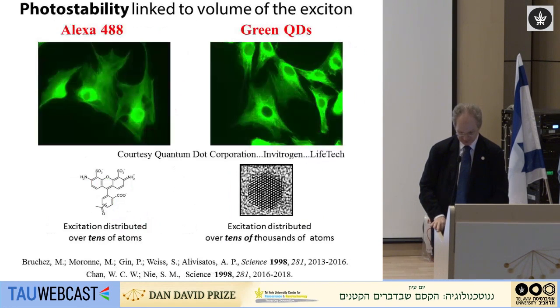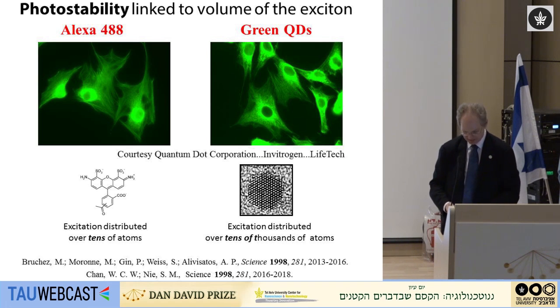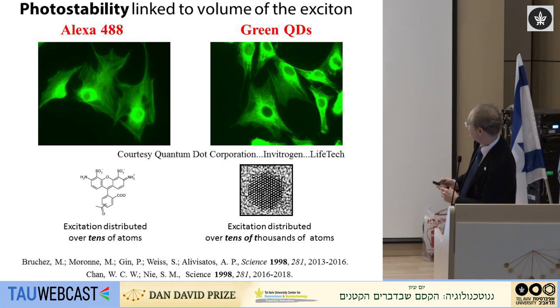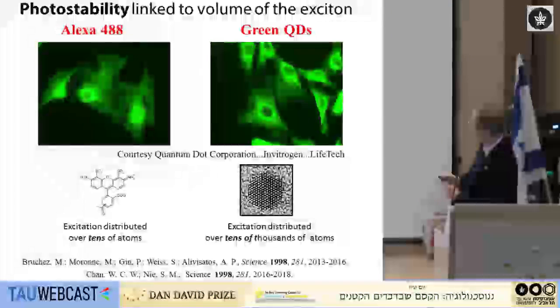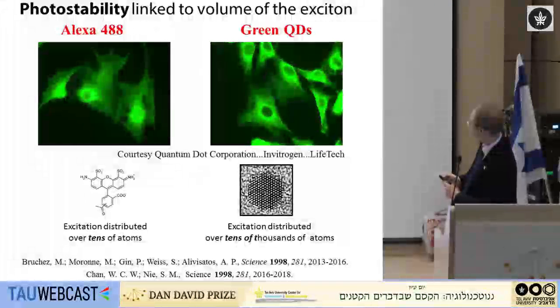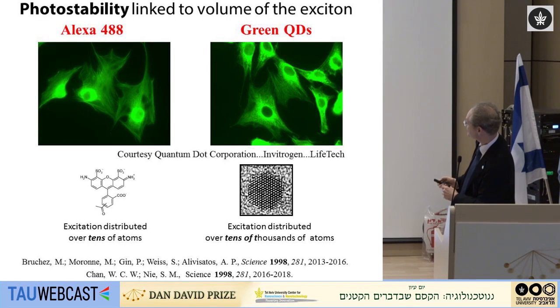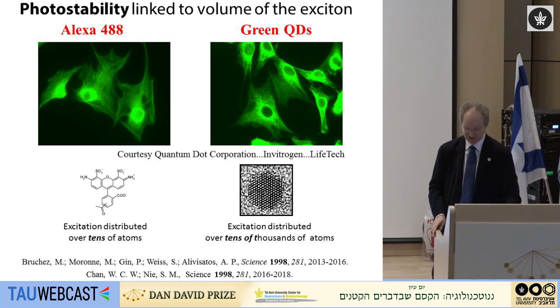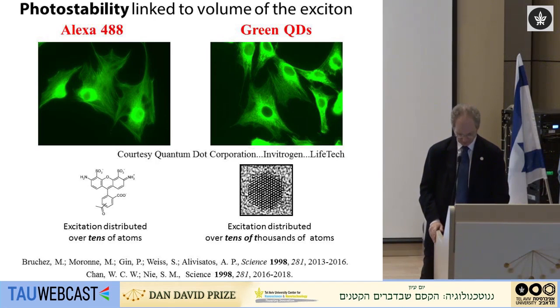So the first application of these quantum dots that we developed some years ago was, in fact, to take them and introduce them inside cells where they could be used for labeling. Here's an example of actin fibers in a fibroblast cell that have been decorated with quantum dots. And over here is the same kind of fiber treatment, but with a common organic dye. During the time that I was speaking, you could see that the dye bleached and the quantum dot did not. And that's because of just what I told you about, that they're more stable.